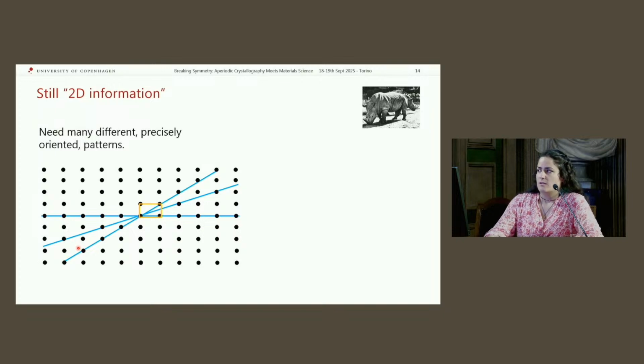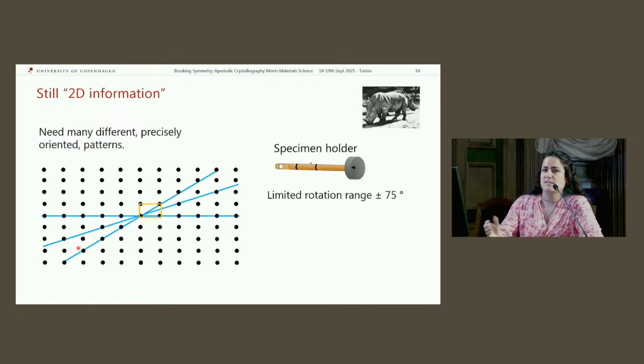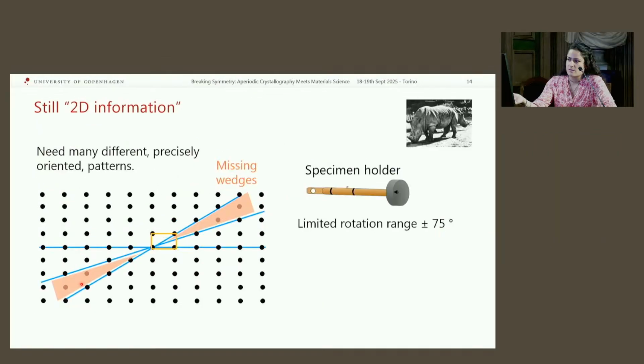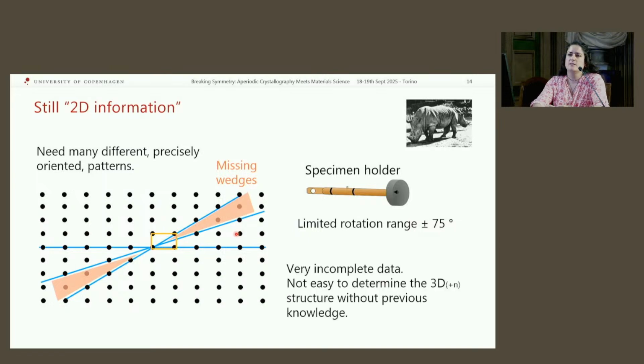To have an idea of the third dimension, we need to rotate the crystals, and ideally we would like to rotate in all directions. Ideally we would like to rotate 90 degrees, but because of the hardware and the experimental setup, it's not possible to rotate 90 degrees. And also when we measure different patterns at different orientations, we are still missing many regions of the reciprocal space. So we have basically incomplete data, and it's very difficult to determine a three or more dimensional structure with an incomplete data set.